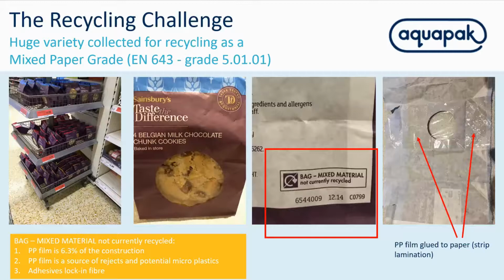So there's an example in terms of what we're looking for here. You've got, as it says there, a bag of mixed material not currently recycled. You have in this case a polypropylene film which is adhered, glued to paper as in a strip lamination. The polypropylene film is about 6.3% of that particular construction, and is a source of rejects and potential microplastics if you attempt to process this material through. So, conventionally these things are rejected.